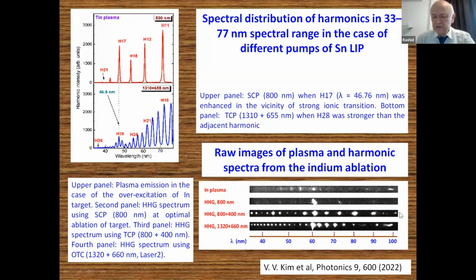This slide shows the generation of a single harmonic and also an enhanced harmonic in the case of two-color pump, when the enhancement of this harmonic becomes not so strong compared to the neighboring harmonic as in the case of single-color pump. And in the case of near-infrared laser radiation, I have shown that this harmonic still becomes very strong compared with many other harmonics and can be used as a source for some other nonlinear optical processes in the XUV range.